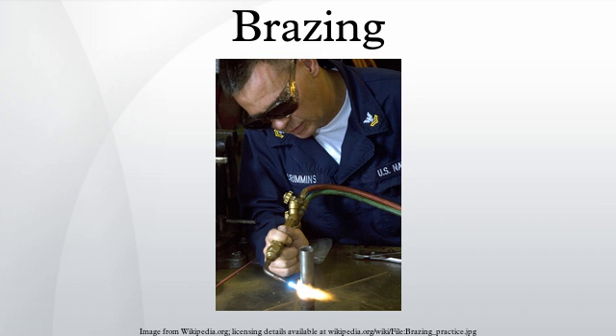The potentially detrimental phases may be distributed evenly through the volume of the alloy, or be concentrated on the braze-base interface. A thick layer of interfacial intermetallics is usually considered detrimental due to its commonly low fracture toughness and other subpar mechanical properties. In some situations, for example die attaching, it however does not matter much as silicon chips are not typically subjected to mechanical abuse.